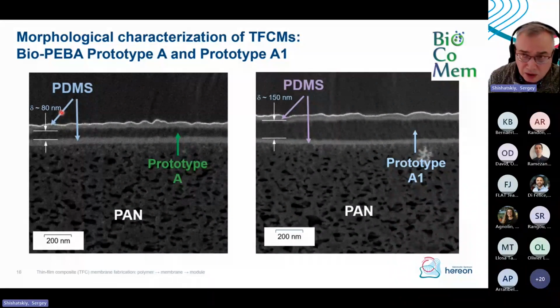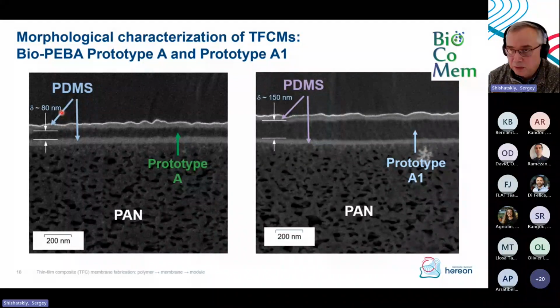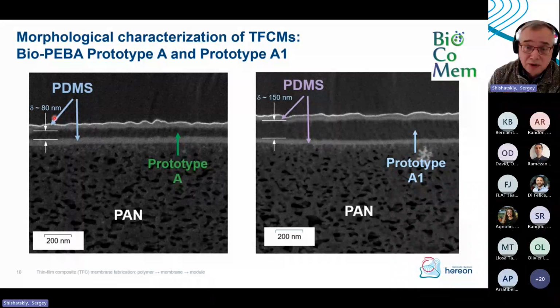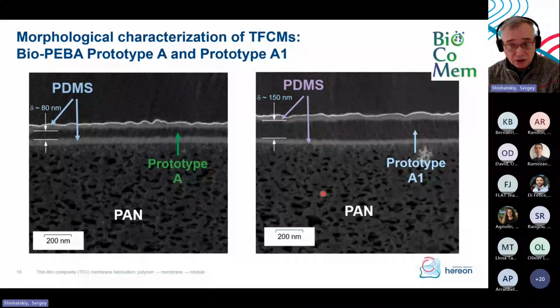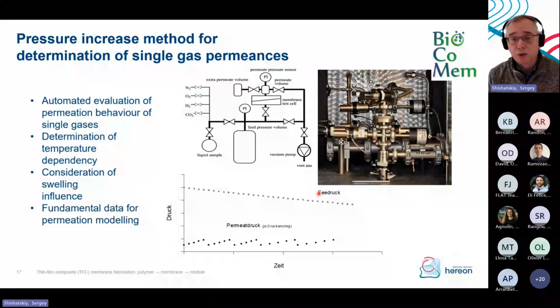80 nanometers means that you need just 80 milligrams of polymer per square meter of membrane. It means that you can use basically any polymer you can find for production of a membrane which can be tested at real industrial conditions. Because 2 grams of polymer is enough for production of 20 square meters of membrane, and that's already a good module to be placed into some industrial environment. So this is a very big benefit of the thin film composite membrane ideology, let's say. Then when we are satisfied with how the membrane looks in an electron microscope, we go for testing, or actually it's mixed between electron microscopy and testing, always, because electron microscopy takes time.